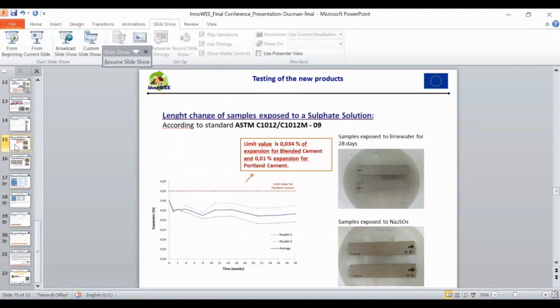The next parameter, which is also related to the chemical stability of the newly developed product, is resistance to sulfate environment. Exposure to sulfate environment in the case of cement can cause expansion and later deterioration. In our case, we exposed our samples to sodium sulfate and tested them for 30 weeks. And again, as you can see here, no expansion was detected. Here are given the limits for cement-based material, because for geopolymer-based material there is no limit set yet. So we need to stick to the cement-based limits and pay attention if anything happens in these systems.